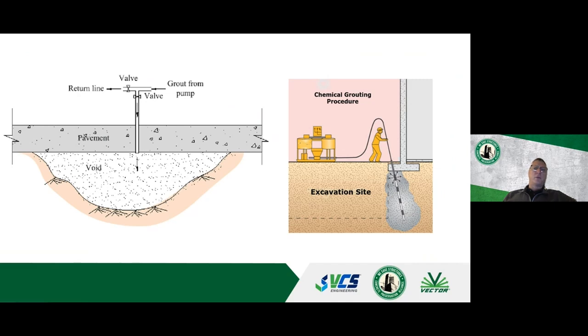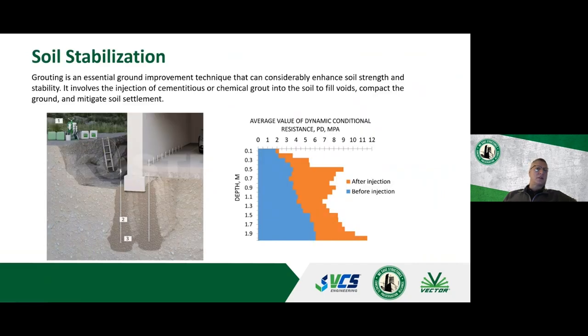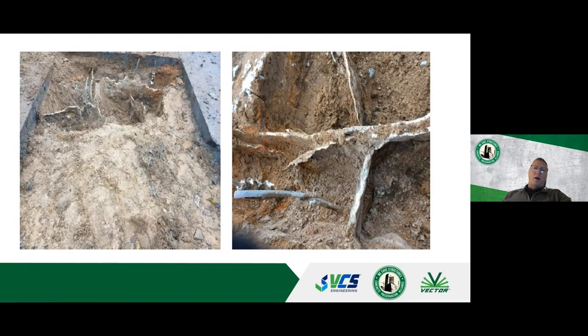And when I say large amounts, I've been involved in jobs where we've gone through 30 truckloads of material to fill the voids underneath. It's amazing what you can do. So soil stabilization is another related subject to this. You're using either a cementitious or a urethane to inject into the soil. So you see on the right-hand side, the strength difference, the before and after when you inject it. These photos are a little bit hard to see, but all of this white that you see was injected through the slab into the soil underneath the slab.